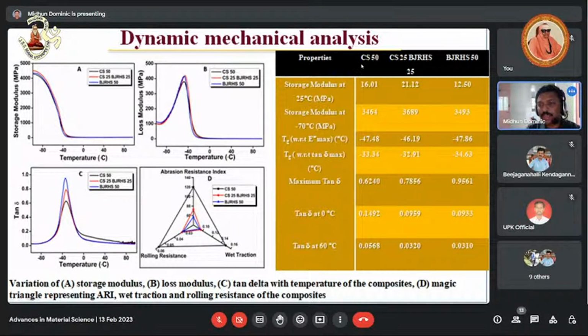So commercial silica, CS50: if we make use of CS50, tan delta at 60 degrees Celsius is 0.05, but tan delta at 60 degrees Celsius for BJRHS is 0.03. So we were able to decrease the tan delta at 60 degrees Celsius, but we have to compromise other mechanical properties. And even though tan delta wet grip is greater, it is 0.14, but it is only 0.09.